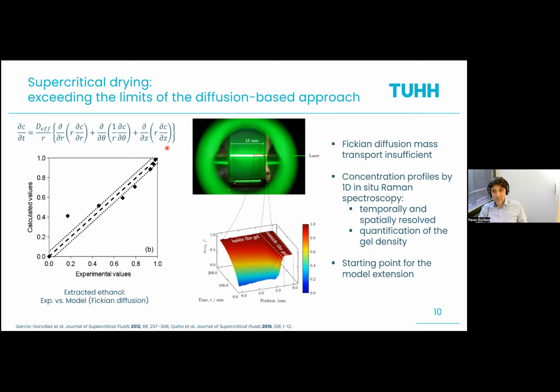But for your creativity to take off, you of course need some experimental data. And for a long time, such data were missing. Only recently, with our partners, with Andreas Breuer and his team around him, we realized that we have to really look into the gel to be able to say, okay, here at this particular place, I have this and that concentration of the solvent and CO2. In other words, you have to spatially resolve the concentration profiles within the gel. And with this information, you can start to model these things.